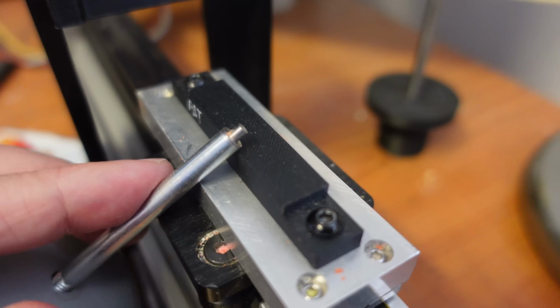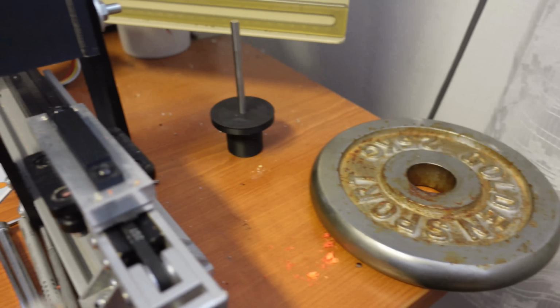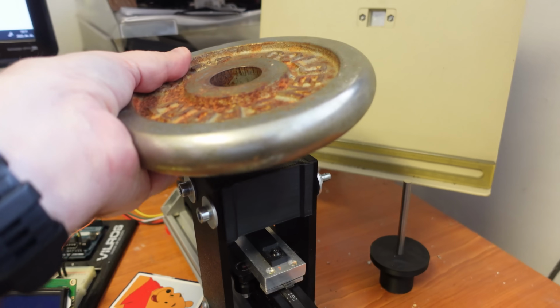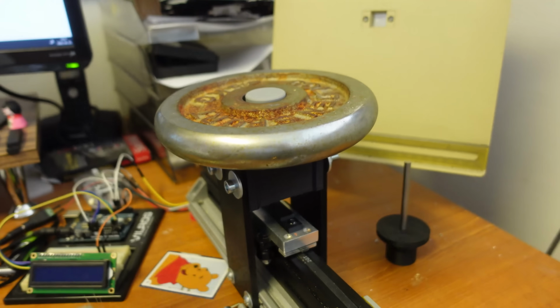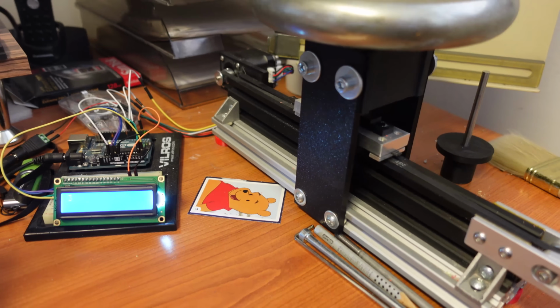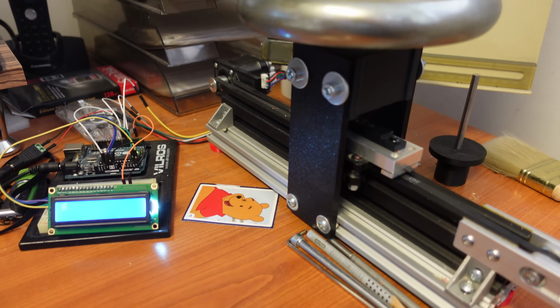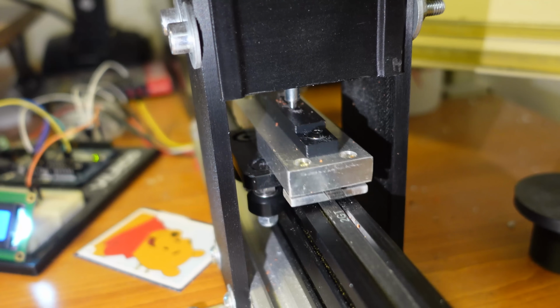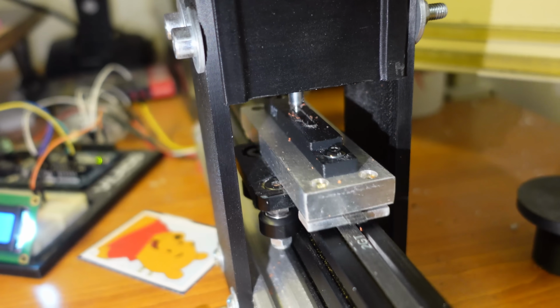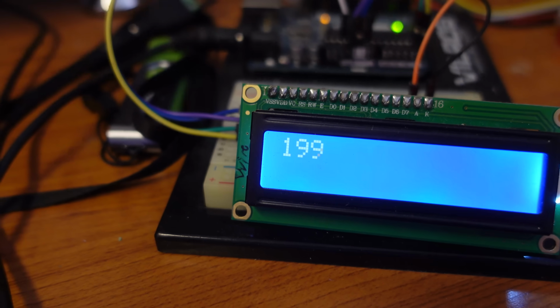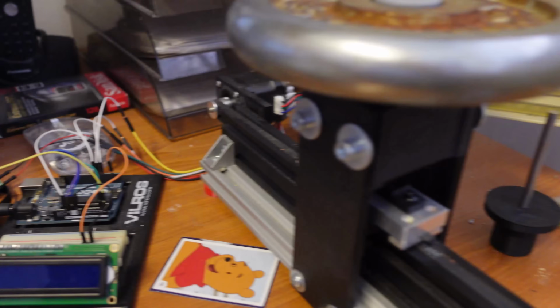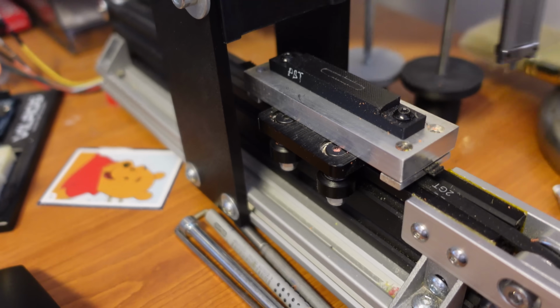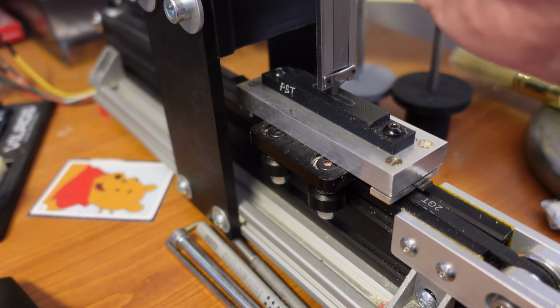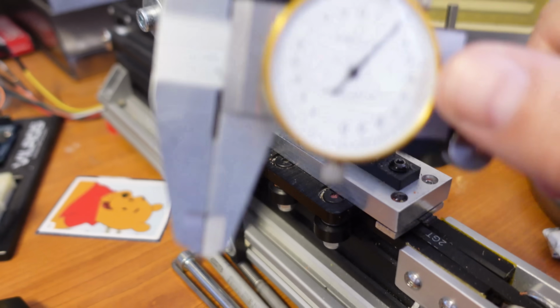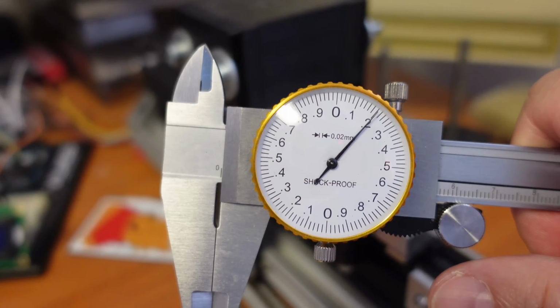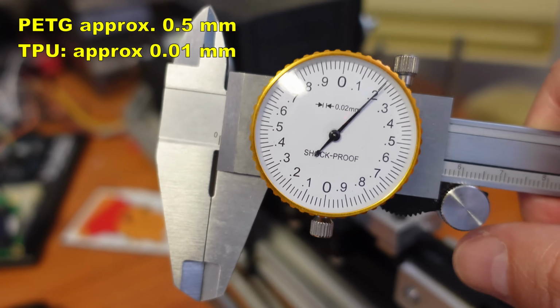Wear test with this 3mm shaft, and the load will be 2.5 kilograms. Test the counter. Even now I can see that it is not as resistant as TPU, but it will have 200 repeats. I cleaned the edges. Let's measure the depth of the groove. It has 0.2 millimeters. Definitely less than average PETG, but more than TPU.